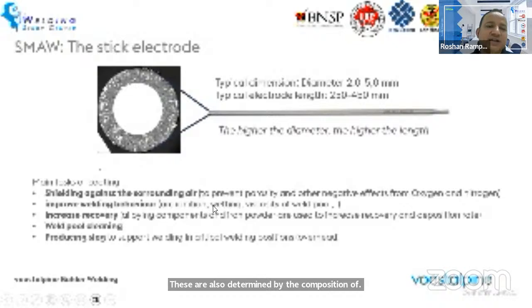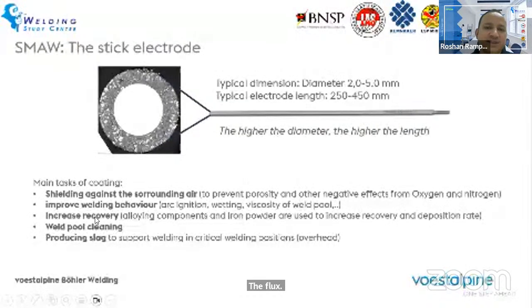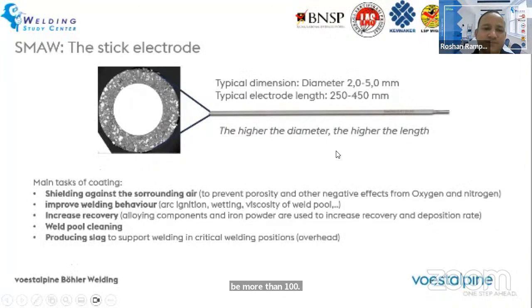It also helps to get higher recovery. Say, for example, E7018. That 18 indicates that the iron powder is added into the flux so that we get higher recovery. So recovery here means when we talk about the total weight of the core wire and how much weld deposit we get in combination of the electrode as compared to the total weight of the core wire. It may be more than 100% also. So this also helps to determine the metal recovery.